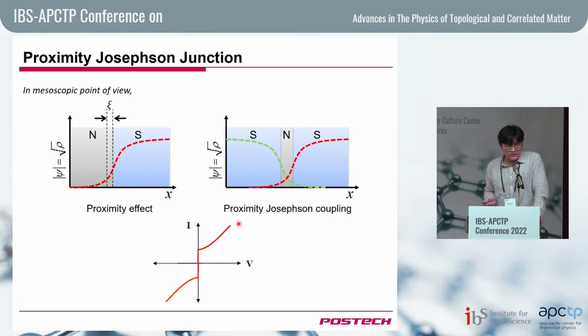That is Andreev bound state. So when we put a superconductor right next to a non-superconducting material, the superconductivity can be induced into the non-superconducting material. This is called the superconducting proximity effect. And if we put two superconductors right next to the normal metal, these two wave functions from the superconductors can form some kind of coupling. This is called Josephson coupling. If that happens, the supercurrent can flow through the normal metal, which is not a superconductor.